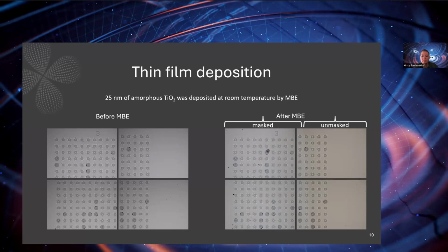And so there's a formula that relates the 2 quality factors so that you can extract the loss of the thin film material itself. And so what we wanted to do with this sample was to test whether it's possible to deposit the thin film on only half of the sample so that we could measure the bare disc quality factors and the coated disc quality factors at the same time, sort of put the chip in to be measured once and carry out those measurements in quick succession.